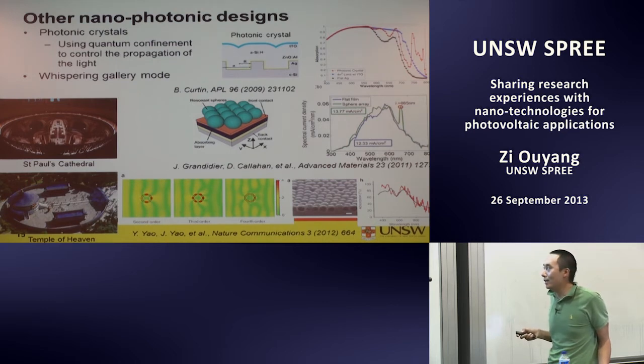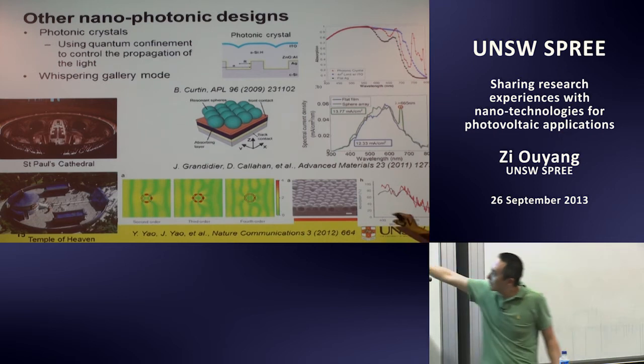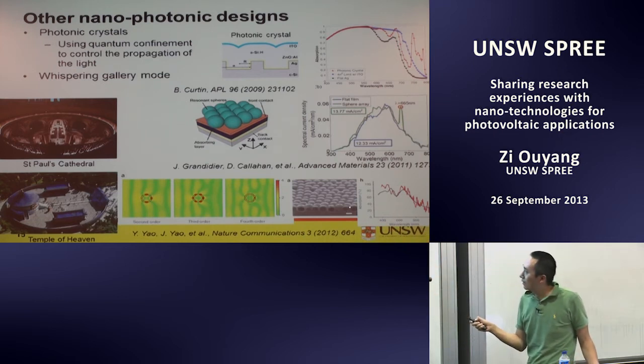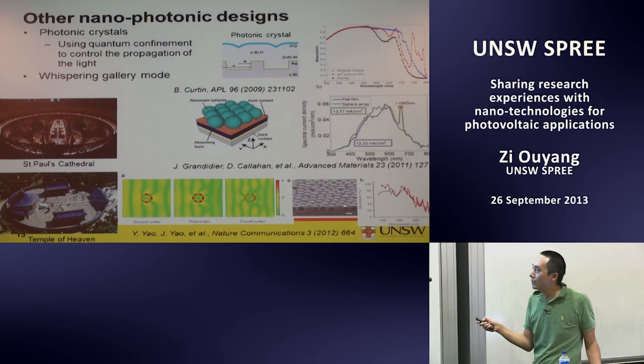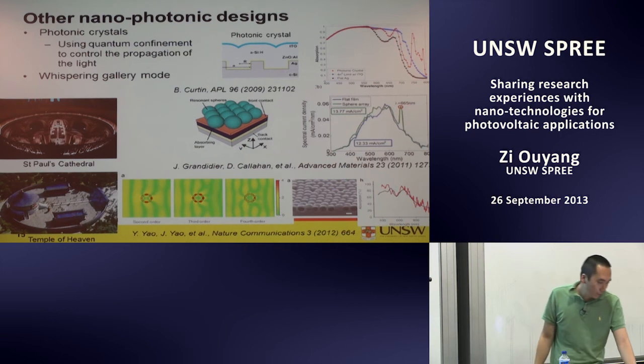They don't have any electrical characterization results, but optically it looks very good. And the absorption is much higher than the thickness itself. What I mean is, if you fill it up with silicon, you actually have less light absorption than this empty hollow structure. So this is something interesting.